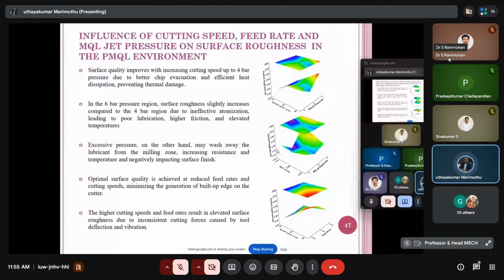So surface quality improves with increasing pressure up to 4 bar due to better chip evacuation and efficient heat dissipation, preventing thermal damage. In the 6 bar pressure region, surface roughness slightly increased compared to the 4 bar region due to ineffective atomization, leading to poor lubrication, high friction, and elevated temperatures. Excessive pressure, on the other hand, may wash away the lubricant from the milling zone, increasing resistance and temperature and negatively impacting the surface finish.